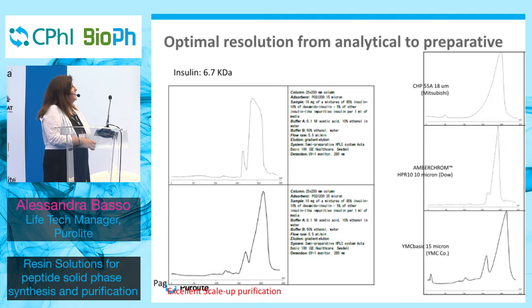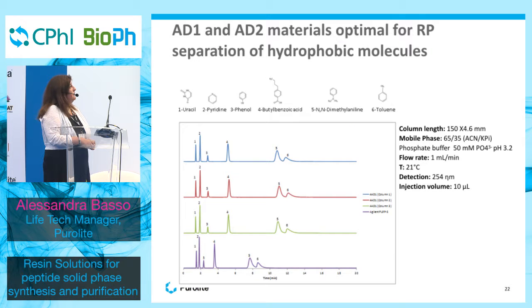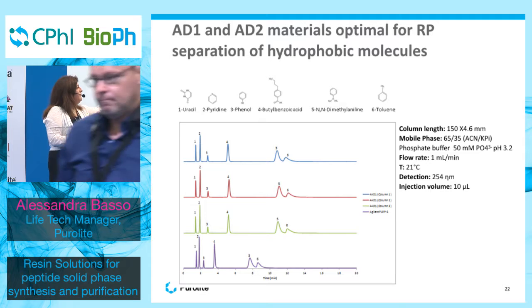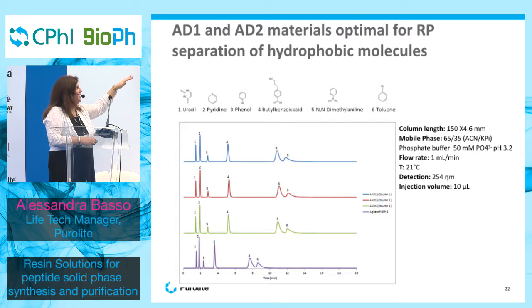The AD materials, so they are the divinyl benzene material, are optimal for reverse phase separation of hydrophobic molecules. And here we report some data on different small organic hydrophobic molecules. Of course, we are not targeting to purify these kinds of molecules, but the target is to show that the performance is comparable and in some cases better than some products on the market, because you get a longer separation, so you can separate some molecules better.